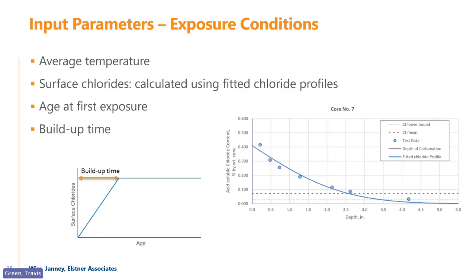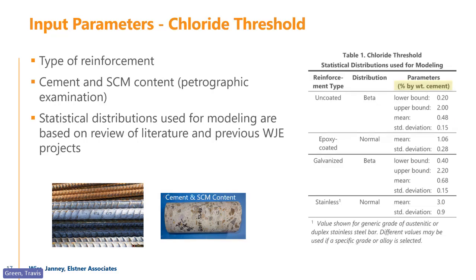When it gets its first exposure, the corrosion's not going to start until the chlorides get to your bars, right? Generally. So if you don't put it on for the first 10 years, you're not going to have to worry about that for the first 10 years. And so then this buildup time is how long it takes to exceed the corrosion threshold. The corrosion threshold, on the right-hand side, we have just kind of changed.